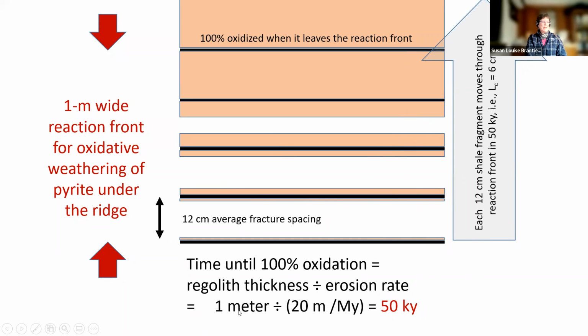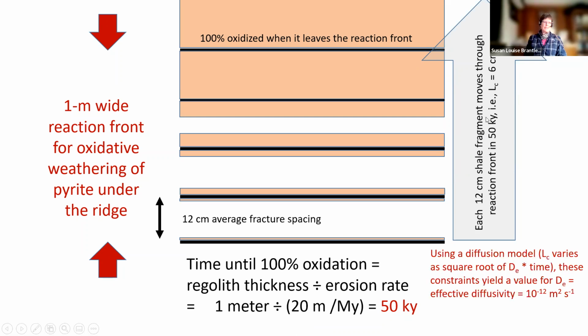So the amount of time that any given one of these pieces spends in this reaction front is 1 meter divided by the erosion rate, 20 meters per million years. So it's about 50,000 years. That means that the oxidation has to happen over 6 centimeters, because it's happening from both directions, in 50,000 years. And so using just a real simple diffusion model, we can calculate an effective diffusivity in this shale matrix of 10^-12 meters squared per second, which is a reasonable number for shales.